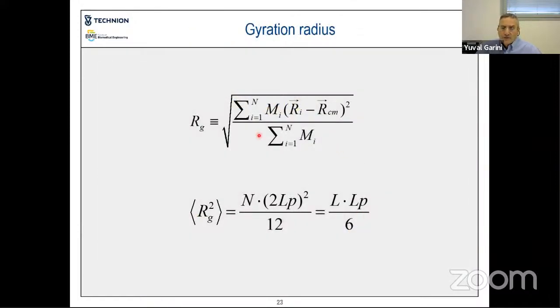This time, we adopted the method of comparing what's called the gyration radius. Roughly speaking, I can say that the gyration radius gives the radius of a circle that the polymer can fit into. It's not exactly that, you can see here the exact definition, but what I said is more or less the physical meaning of that. We know well what should be the average of the gyration radius for an ideal polymer. You can see it here based on the nominal length and the persistence length of it. The point is that we don't have an exact equation for the distribution of the gyration radius.